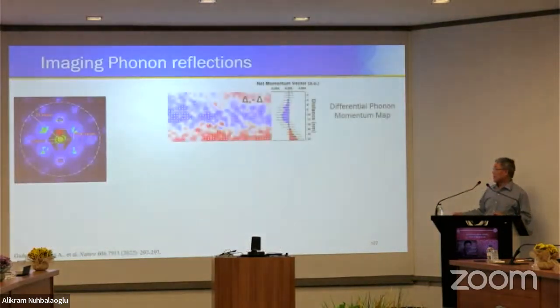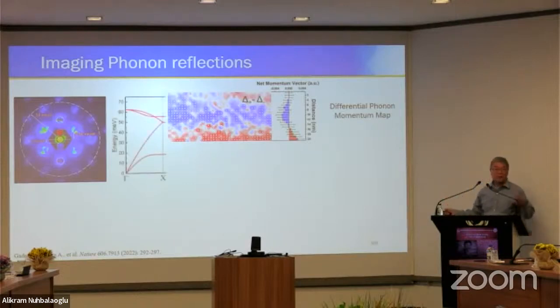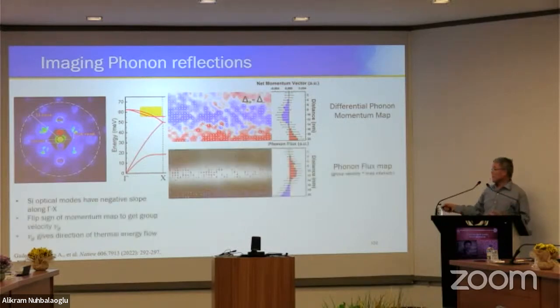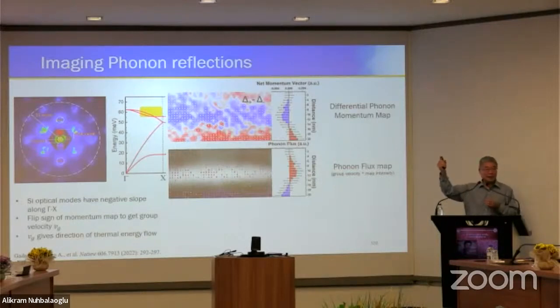And that is great. Now, if this is true by model, can we directly measure the direction of phonon propagation? In other words, can we measure the momentum direction of the phonon? So this is another method we developed in this work, and probably the same paper. So we just measure the phonon with two different kinds of cuts of the momentum of phonon. One is a plus, another is a minus. And then we have two maps and subtract them from each other. This is called differential mapping. The differential mapping will tell you what is the net direction of phonon change, right?